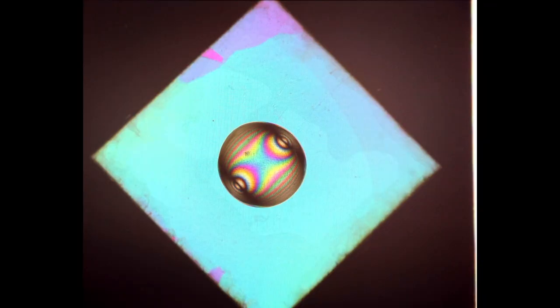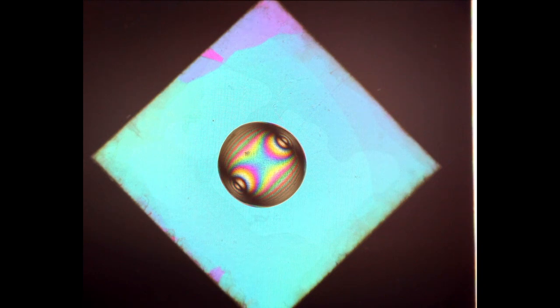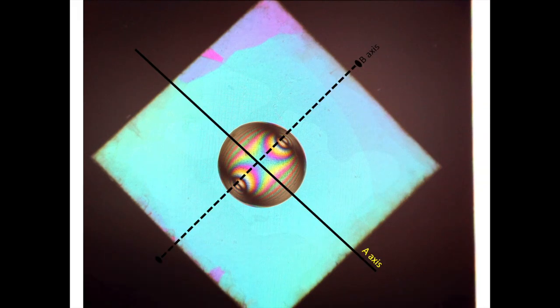So if we know where the melatopes are in our interference figure, we also know where our B crystallographic axis must lie. Using our combination of the crystallography of the cleavage planes of our muscovite mica to find the plane of the A and the B axes, and then our optical properties in order to pin down exactly where the B crystallographic axis is, we've now fully oriented our muscovite mica sample, and we can add on our C crystallographic axis as well, as we know where it must lie given its relationship to our A and B crystallographic axes. The C crystallographic axis will be perpendicular to our B crystallographic axis and inclined at 95.5 degrees from our A crystallographic axis. So that is the most important part of what we were doing today, using a combination of crystallography and optical properties in order to understand the orientation of our muscovite sample.